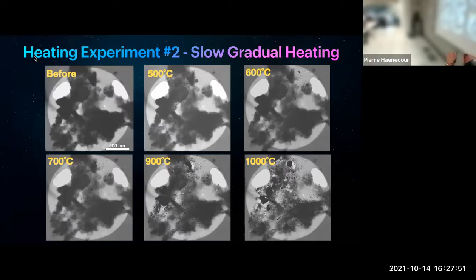As the sample is heated to higher and higher temperature, you basically create more and more of those nanoparticles, accumulating in the sample. I'm going to show you in a minute that it actually moves the iron. It actually melts your sample, and you can see the iron moving, swimming around in this matrix of carbonaceous material.